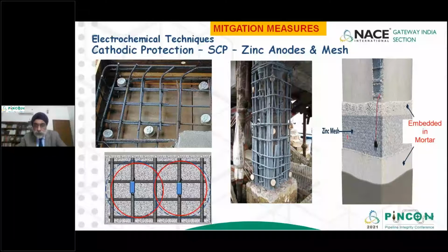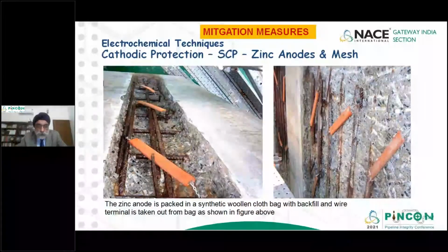The zinc mesh is electrically connected to the rebars, and it continues to provide current and sacrifices itself but does not allow the rebars to corrode. You can see again some photographs of zinc anodes which have been embedded on a structure where the rebars have completely corroded. So this is the zinc anode.